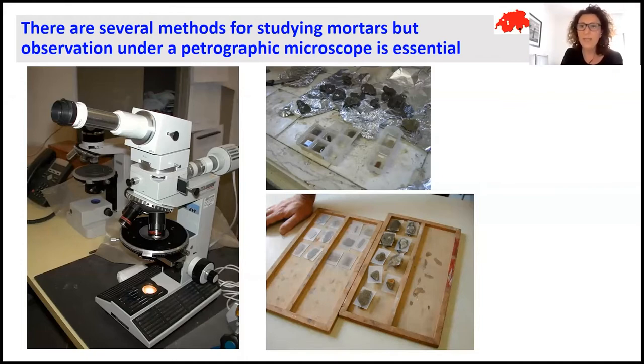To make it possible, the mortar sample should be prepared as a thin section. The thin section preparation starts with the sample being embedded in a resin in order to make it stronger. Then the sample is applied on a little glass surface, and after the different cutting and polishing, we should obtain a thickness of the sample of not more than 30 microns. This is because we need to observe with the petrographic microscope using transmitted light. So it's necessary that the light should pass through the sample.